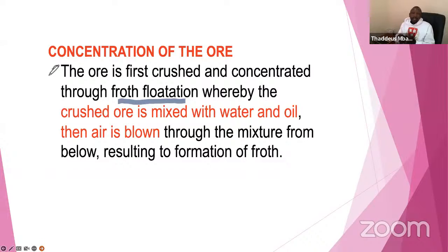Yes. So the ore is first crushed. Normally, the concentration of the ore is done using a method called froth flotation, whereby the crushed ore is mixed with water and oil. Then air is blown through the mixture from below, resulting in formation of the froth.